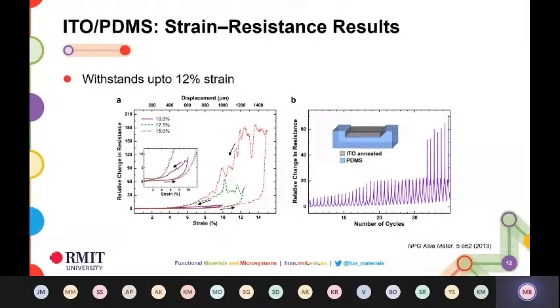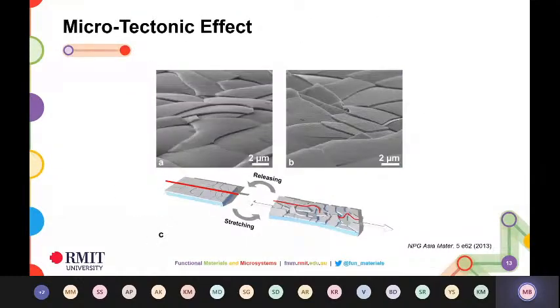We then thought, okay, we managed to do this. Now, let's see how this actually withstands some strain. So we strained this, and we were quite surprised to see that 3-4% is probably the max it might withstand, but we found it withstood up to almost 12%. And even if it became open circuit, once you again brought it back to 0% strain, it again recovered its original performance, and you could keep reusing it. So we were thinking, how did this happen? How is it possible that an oxide layer, which is usually quite brittle, is able to withstand quite high levels of strain?